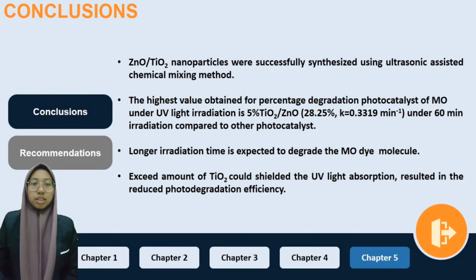In conclusion, the titanium dioxide doped zinc oxide nanoparticles were successfully synthesized using the ultrasonic assisted chemical mixing method. The highest percentage degradation of methyl orange under UV light irradiation is obtained with 5% titanium dioxide doped zinc oxide, which is 28.25%, and the rate constant is 0.3319 per minute under 60 minutes of irradiation compared to other photocatalysts.